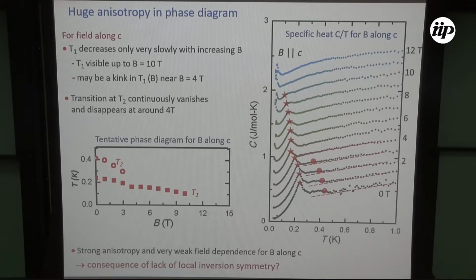Then we also look at the specific heat at low temperature for field applied along the c direction. And there you see that we found a huge anisotropy. The transition at T1 moves only very, very slowly down in temperature and can be followed up to 10 Tesla, while the transition at about 350 or 400 millikelvin just slightly goes down and then disappears. So we have a very strong anisotropy and a very weak field dependence for B along c. And there is the question whether that might be a consequence of the lack of local inversion symmetry at the cerium site, whether that might suppress the effect of a magnetic field along the c direction. There are some predictions along this direction.